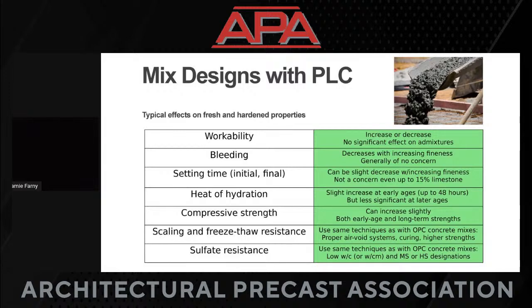That little bit of extra fine stone of limestone, and because it's a finer ground cement overall, it may have some slight impacts. Maybe it's going to decrease your overall bleeding. It may delay it, it may decrease it, because again, the mix is very tightly bound with that particle packing going on. The water can't work its way to the surface. You might see a little decrease as your materials get finer, but at the 15% limit that we're talking about, the setting time, that slight decrease that you might see, either initial or final, it's really manageable. And if it is somehow a concern, again, you can turn to tweaking your admixtures a little bit.